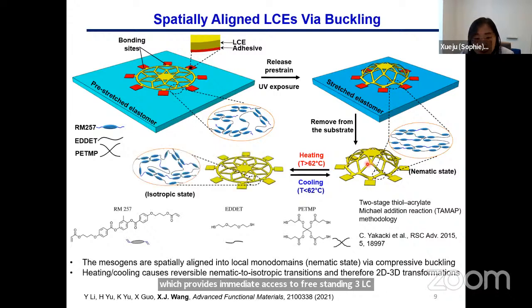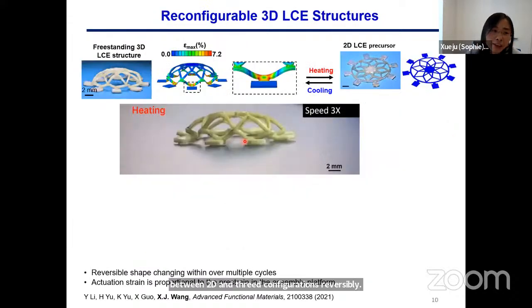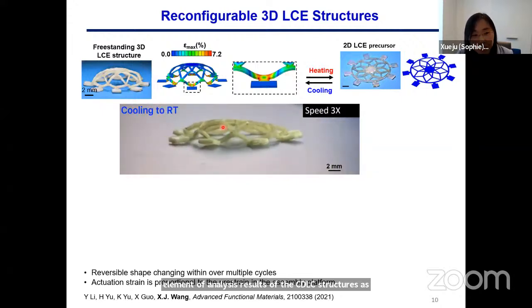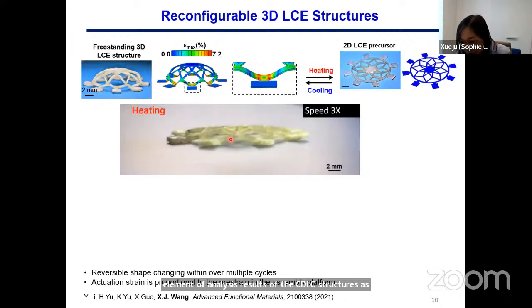By heating and cooling across the isotropic clearing temperature, which is 62 degrees for this material used in this study, we can morph the structure between 2D and 3D configurations reversibly. Okay, so here are the experimental and finite element analysis results of the 3D LCE structures, as well as the dynamic shape morphing behavior of the structure.